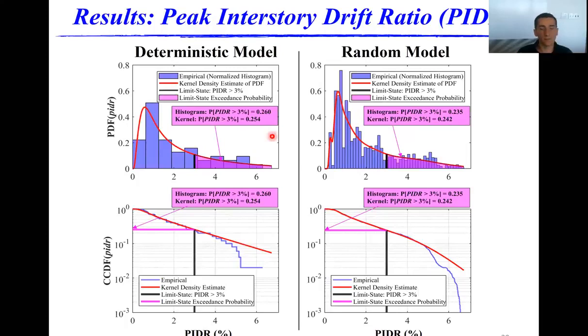We have more data points that are above this 3% drift. We have actually 13 in the deterministic case. So 13 is a better number than 4 because it's less sensitive to a small increment up or down. And again, we have very good agreement on the random model results.